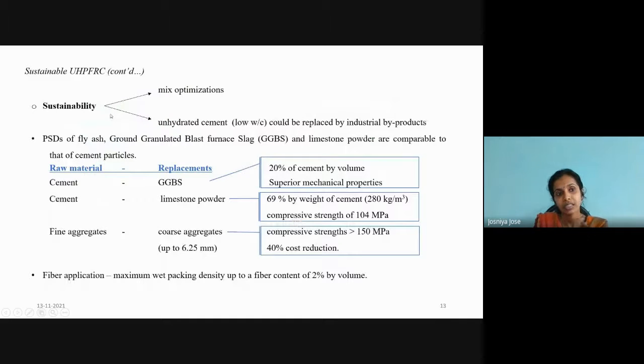So how can we achieve this sustainability in UHPFRC? And that's by mix optimization and replacement of unhydrated cement by industrial byproducts. Since it contains a lower water cement ratio, most of the cement will be unhydrated, and that can be effectively replaced by industrial byproducts like fly ash or GGBS or limestone powder.